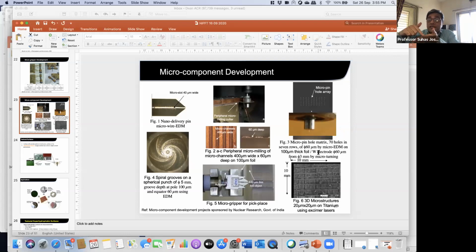And what we say is that the difference in the first hole and the 70th hole should not be more than 1 micrometer. So diameter should be 60 micrometer, and first and last hole should not have the circularity error more than 1 micrometer.